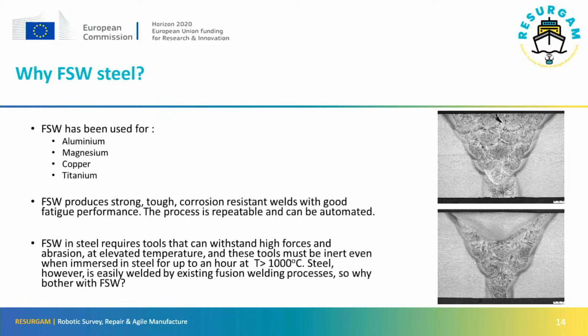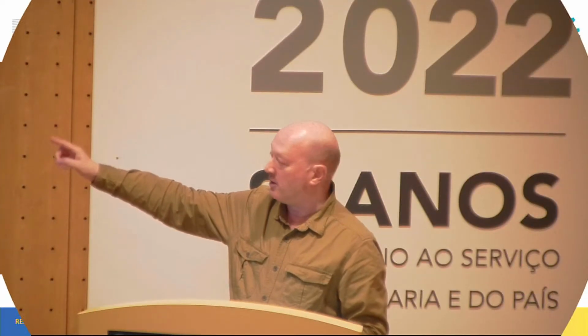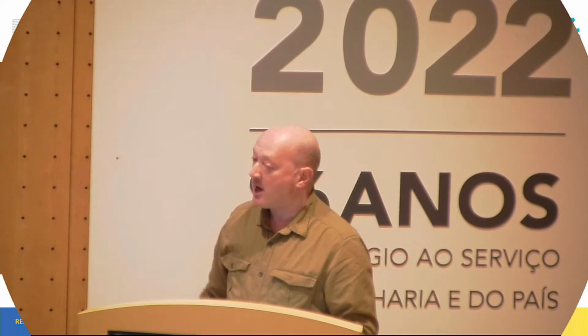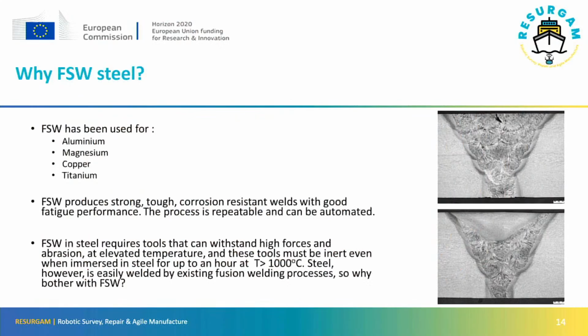That's the friction stir weld. So you can actually compare the friction stir weld microstructure with a cast arc welded microstructure and the parent material. And I think you can see that the friction stir welded structure is very similar to the parent. So it shouldn't be surprising that the properties of the friction stir weld are at least as good as the parent metal.